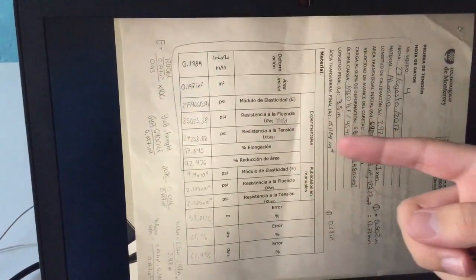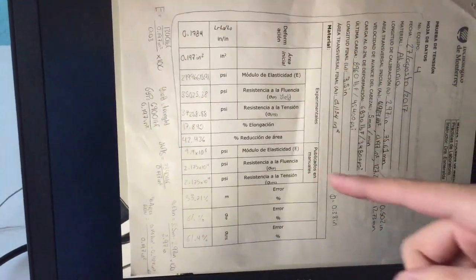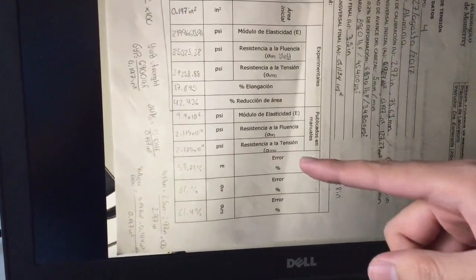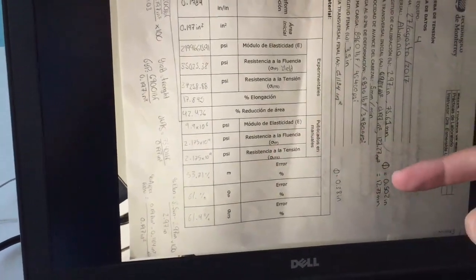As we can see, the results in the chart that we got and the results that are published are quite different. Here we can see that the elasticity modulus is around 21 million psi, while the yield strength and the tensile strength are around 35,000. While in the published results, the elasticity modulus is around 9 million and the yield strength and the tensile strength are around 21,000. That means that we got higher results. That was the aluminum chart.